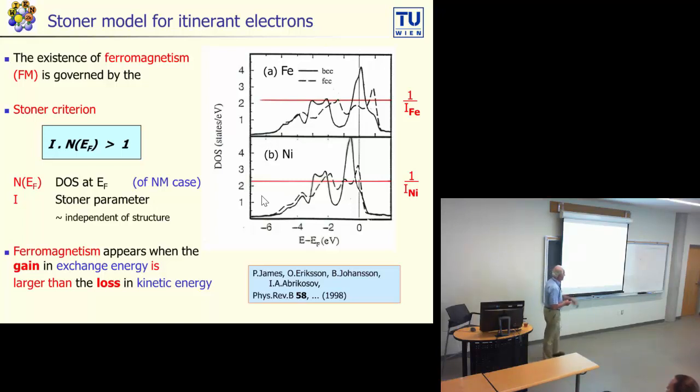What Peter just showed with phonons, you have the same thing in magnetism, it is the curvature at the non-magnetic case, the energy going up or going down. If it's going down, there must be a magnetic solution. If it's going up, it stays non-magnetic. And the criterion is the Stoner criterion. If the density of states is high at the Fermi energy, the Stoner criterion is satisfied.